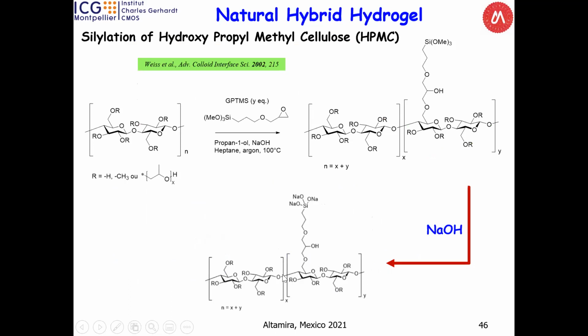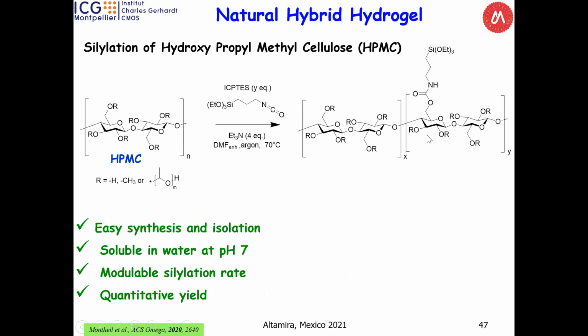Okay, really, it's my last example now. So we move to natural polymer. It's not synthetic polymer. So we took hydroxypropyl methyl cellulose. The idea is to silylate it. Some groups in France silylated it before us, but the problem is that after their silylation, it was necessary to apply alkaline treatment to isolate their polymer. And it's a very big problem for cell culture because you have to neutralize, and it's not so easy. Our idea is to silylate it directly and use it as isolated, without any acid or base treatment.